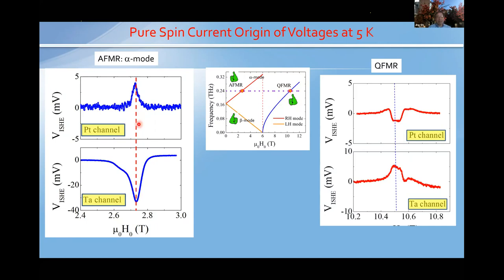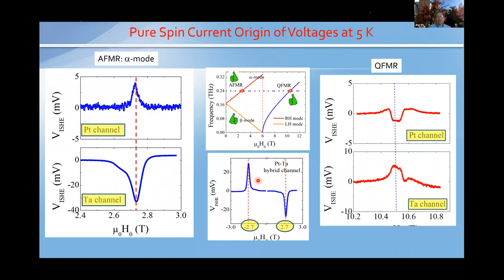Okay, how about the negative field? Here we changed the detector. So how about we change the source, to change the angular momentum, or spin polarization, in the source? We sweep the magnetic field to the negative side, and we have a complete reversal of the peak voltage. There's no finite shift or anything. It's zero background and a completely inverted voltage signal. So these two sign reversals give us confidence that the detected signal is indeed from the spin current of resonantly generated coherent magnons.